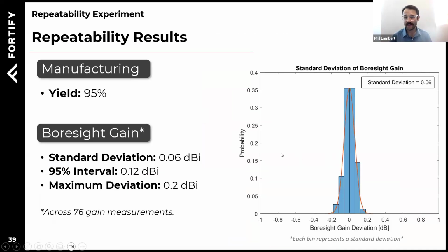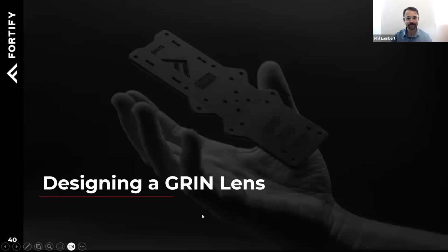And the results were great. So we had 95% manufacturing yield. And what we're doing here is just measuring boresight gain. So we don't have a chamber that allows us to create complex beam patterns. So we're just looking at boresight gain on our VNA and measuring that across 4 different positions on each lens across 19 lenses. So it ends up being 76 gain measurements. And across all 76 gain measurements, we saw a standard deviation of 0.06 dBi with a maximum deviation of about 0.2 dBi. So from our perspective and from our customers' perspectives, that's very repeatable. So we're very happy with that result.